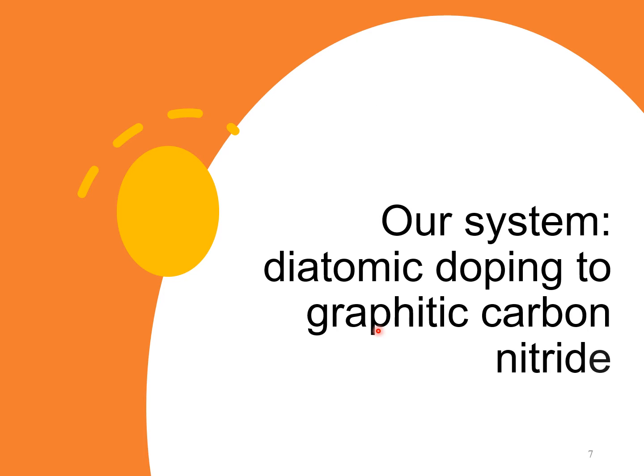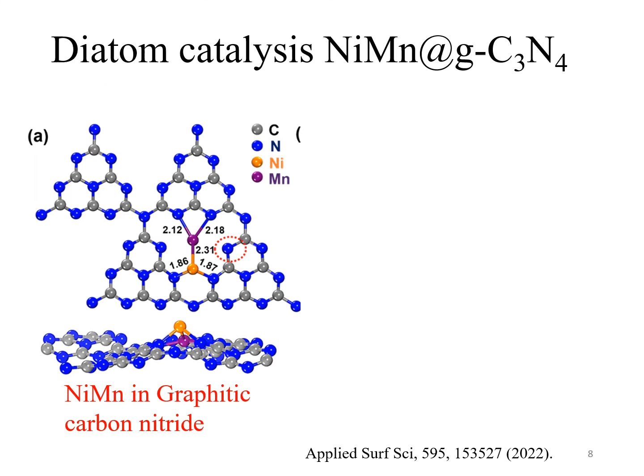Our system is the diatomic doping of transition metals to graphitic carbon nitride. We decided to study doping nickel, manganese into graphitic carbon nitride. Here, carbon is given in gray, nitrogen is given in blue, nickel is orange, and manganese is purple. And this system has been experimentally realized. So there are reports of using this surface.